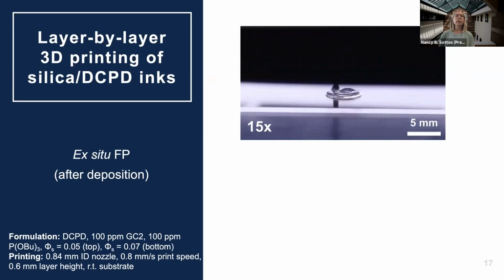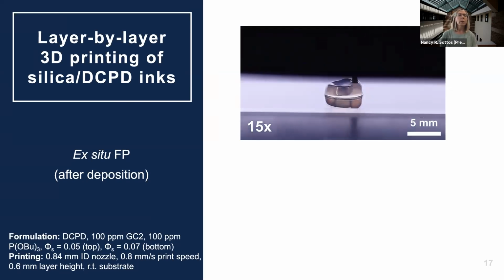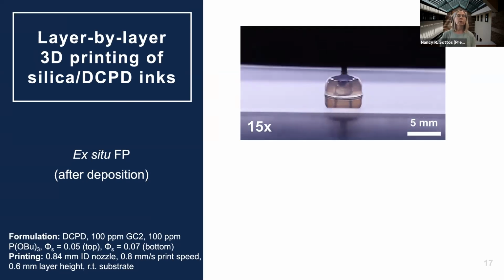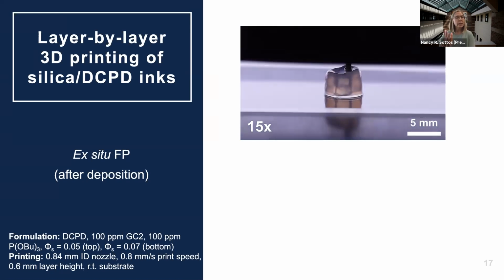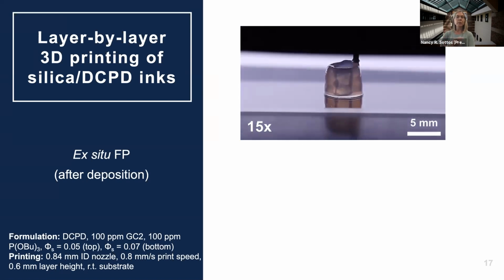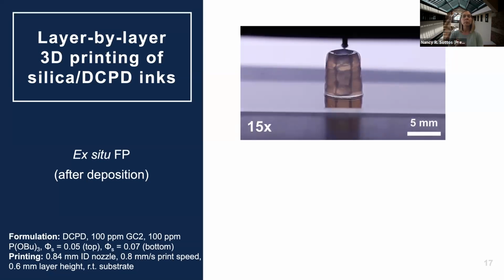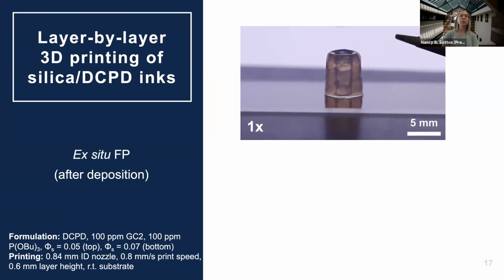And you can see that we can create an ink with a very different viscosity. This one's gelled a little differently. And in here, we're just creating an annular structure, layer by layer. And this is a little bit different example, because instead of curing on the fly, in this case, we're just writing with the gel-based ink. And as you'll see, the frontal polymerization is going to be initiated ex situ. So there's our structure. There's the soldering iron in this video. And you can see it's just going to be touched there for a second. And this whole thing will now frontally polymerize after the fact.